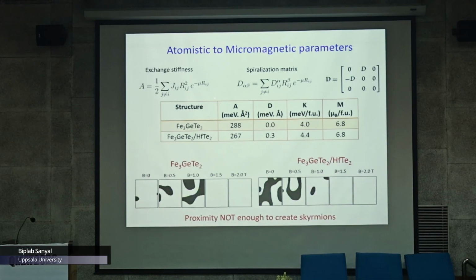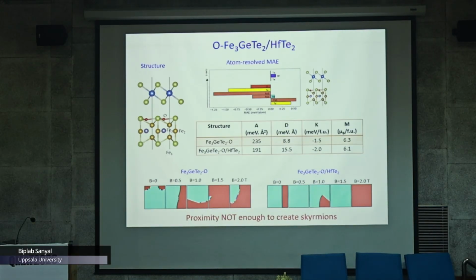Because I said that these parameters must work together in some specific ways if you want to see any skyrmionic formation. So next we thought that, okay, some people have said that maybe the FGT systems are oxidized, and that's why you see the skyrmions. So we had a model here with some oxygenated part. And then we did exactly the same things. We calculated the parameters and we did micromagnetic simulations, but still we did not see any skyrmion formation.